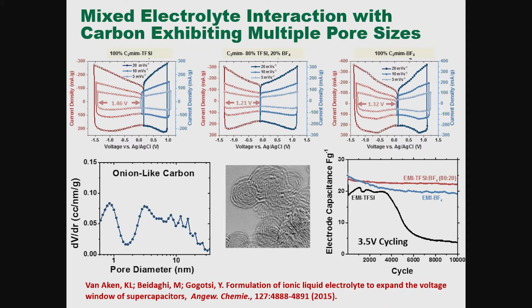How does that interact with a mixed electrolyte? As Majid talked about this morning, the pure C2MimTFSI shows this asymmetrical behavior of the two electrodes during charge-discharge cycles. Also, a pure C2MimBF4, much smaller anion, shows this asymmetrical behavior, but a mixture of the two, a magic mixture 80-20, gives a perfectly symmetrical behavior.